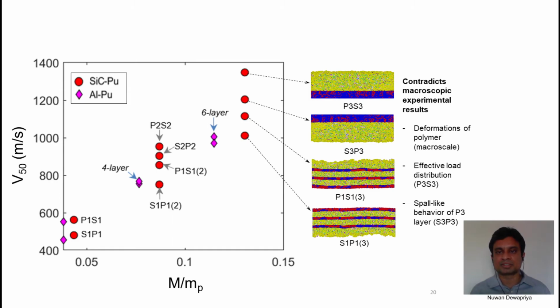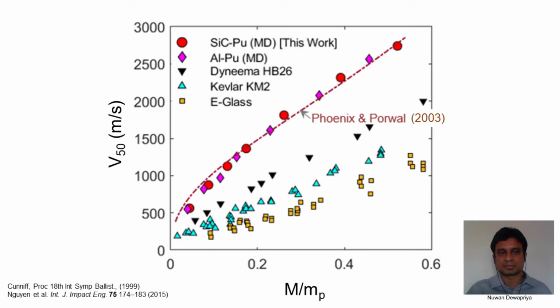Viscoelastic and plastic deformations of the polymer layer on the back face absorb more energy at the macro scale, but we observe that the propagating shock wave generates spall-like failure in the polymer layer at the back face. In contrast, the failure of the polymer layer on the strike face is more like shear plugging and it effectively distributes the shock loading to the underneath ceramic layer. Here we compare the V50s of nanoscopic multilayers with macroscopic barrier materials such as Kevlar, and the nanoscopic multilayers have significantly higher V50s.